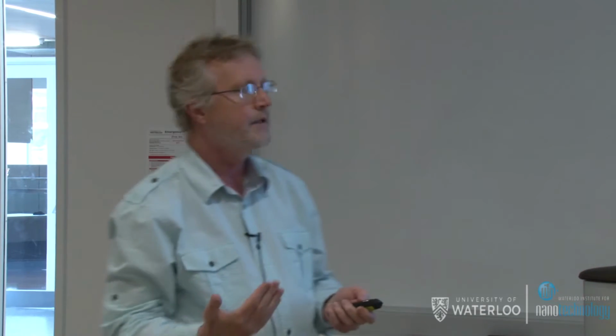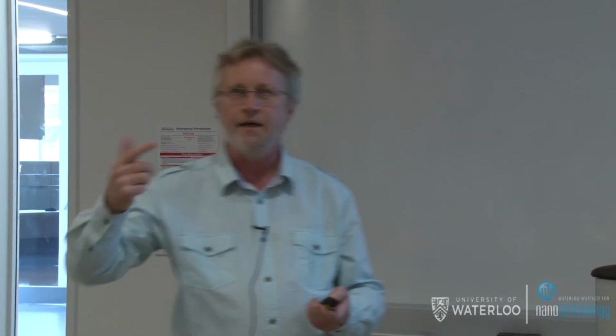Another interesting thing appears if they become spontaneously tilted, like the molecular plane is tilted with respect to the layer normal. Then they become chiral, not only polar, but chiral. But now the chirality is coming due to the polarity and the tilt. And this specific phase has 4 subphases. It can be anticlinic, synclinic, ferroelectric, and antiferroelectric. So 2 times 2, 4 possibilities.